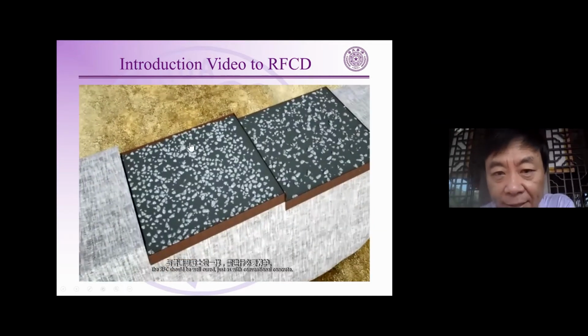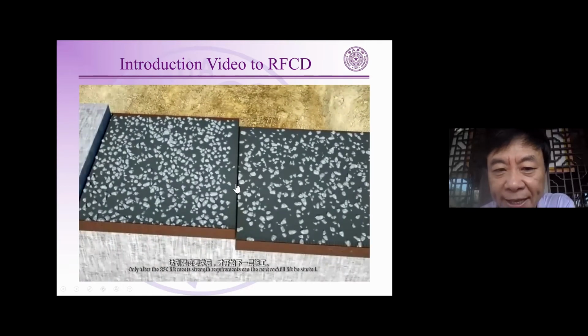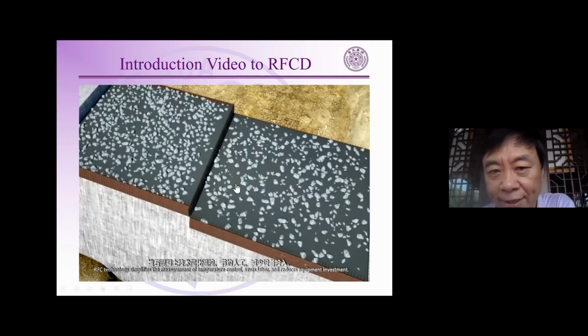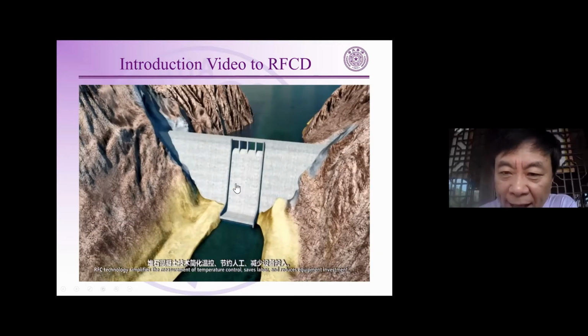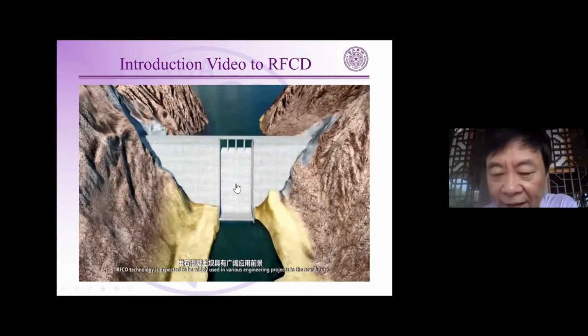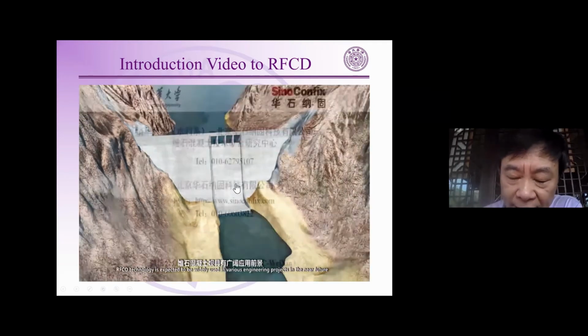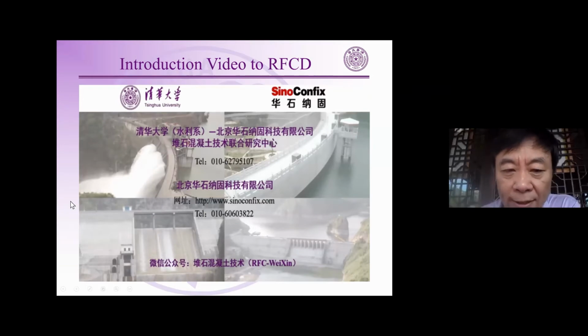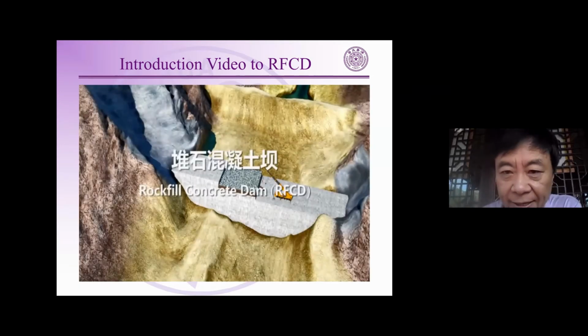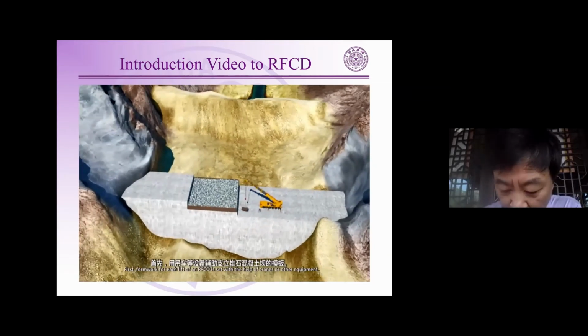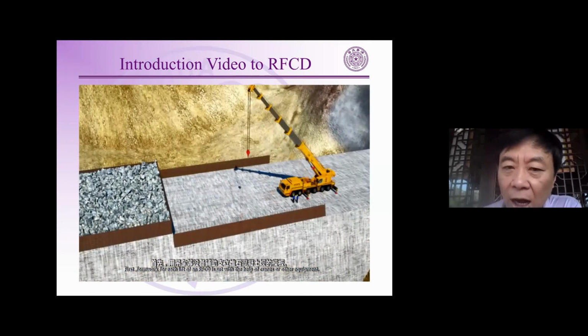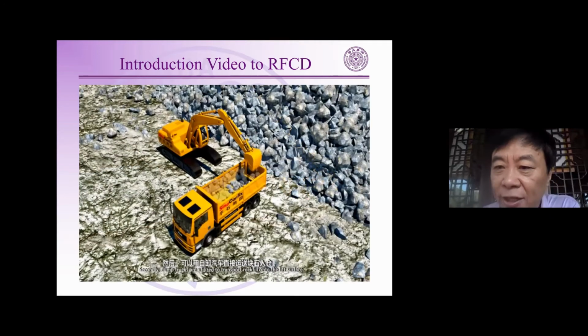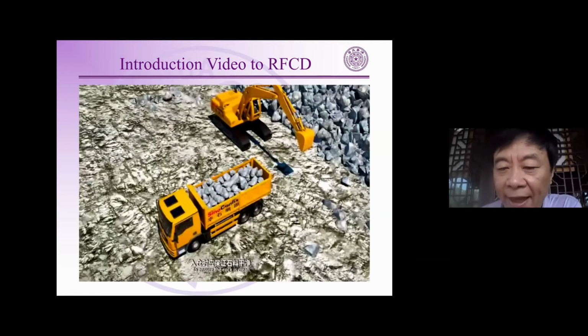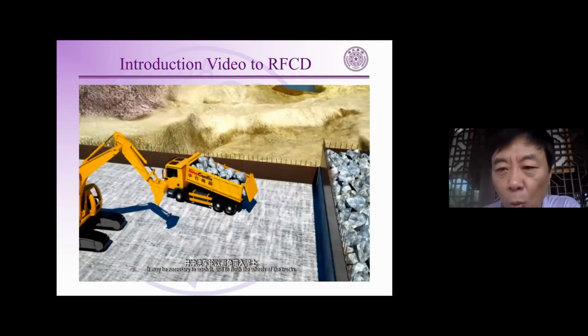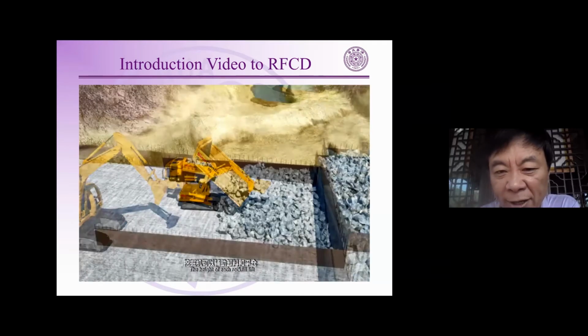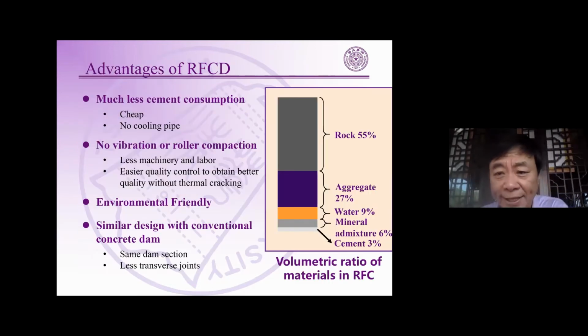And you can see at the lift surface, we let some of the rocks stay above the surface of the self-compacting concrete, and then the upper and lower lifts can be bonded to each other with these exposed rocks. And of course, because these new techniques use so many rocks, very little cement is used. And due to the very low cement consumption, the thermal stress in this concrete is very low, and then there are no temperature control measures.